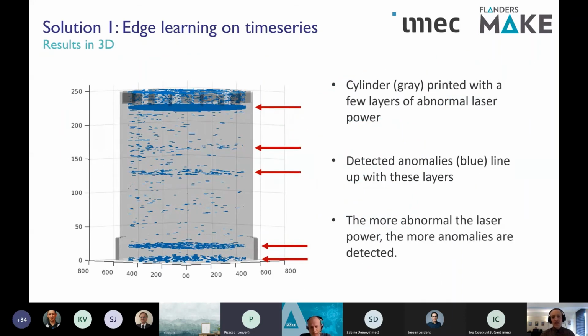So we took this concept and we tested it on a 3D build of a cylinder that you see in gray on the right here. And our anomalies that we detected are shown in blue. And what we saw is that the anomalies we detected tend to line up to layers that were created with an abnormal laser power in the machine. So this is good that we're seeing this correlation.